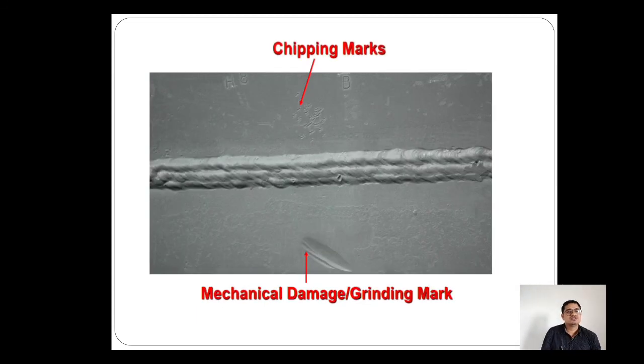So see the figure, you can see that on the top side of the plate there are chipping marks, where the welder is trying to remove the slag from the welding bead, but unknowingly he put the chisel on the parent metal. On the second side, due to some wrongness, he used grinding over the parent metal. Due to this, the thickness of the parent metal got less.